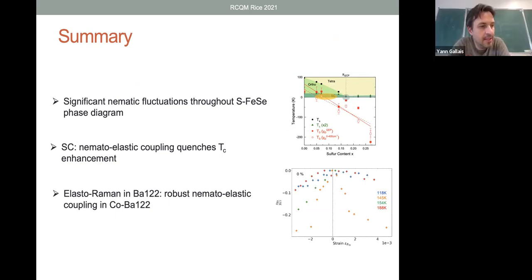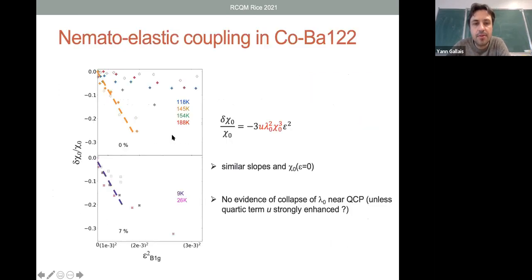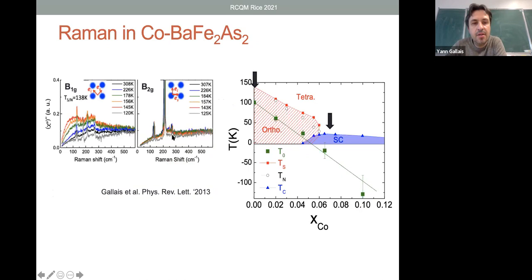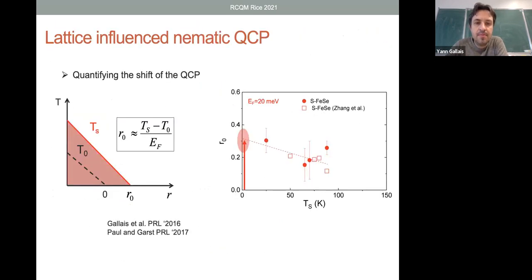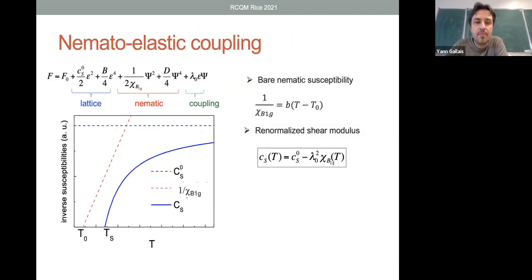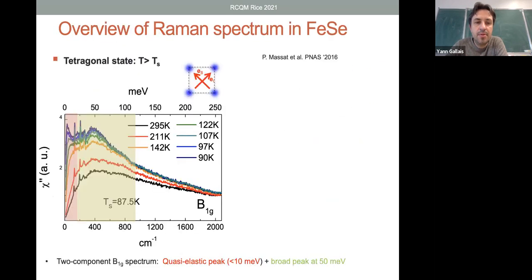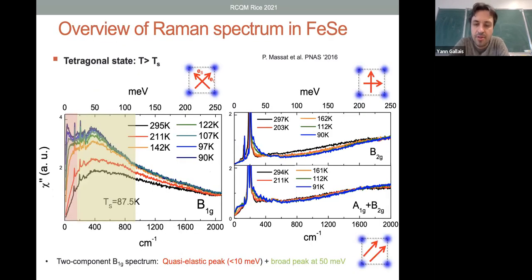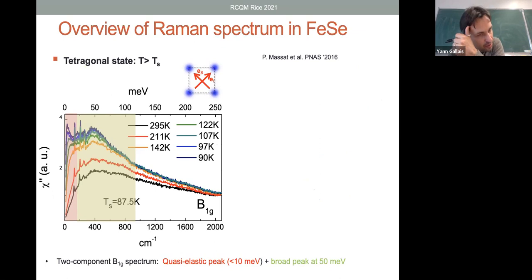Okay, so this is more like a matter of interpretation. As I mentioned at the beginning of my talk, let me just show you this. If you look at the Raman spectrum of iron selenide, it has these two components. You see there is this low energy component that I highlighted in red, that we believe is really associated to itinerant carriers.